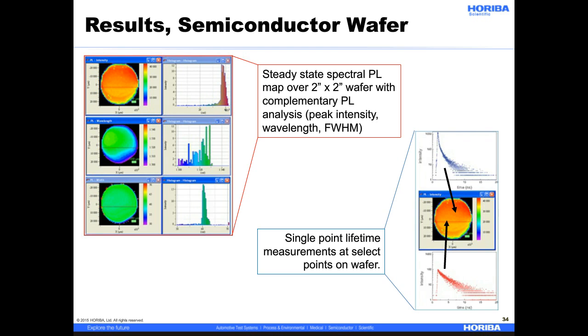By measuring the lifetime in semiconductor samples, the user can probe the dynamic processes in the sample under test and assess the quality of the material. In addition to spatially identifying areas on the sample, the use of a spectrometer in this system also allows for lifetime measurements to be made at different wavelengths in the PL spectrum. In a filter-based system, the user would be restricted to a set of wavelengths and bandpass dictated by available filters. The new MICOS hybrid PL system provides much greater flexibility with virtually limitless choices for detection.